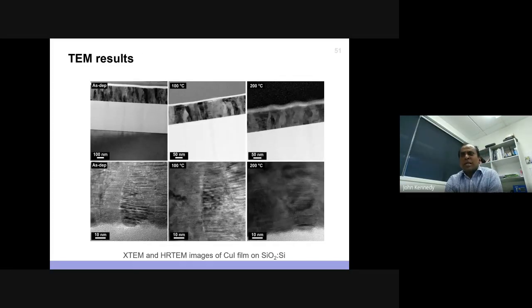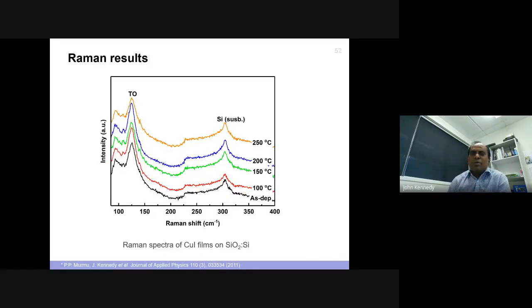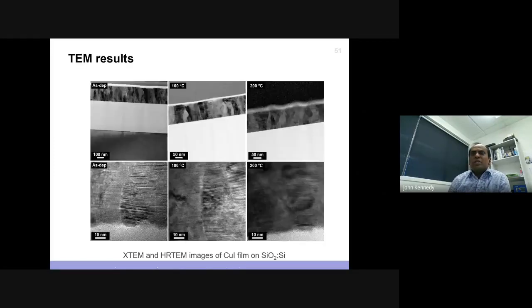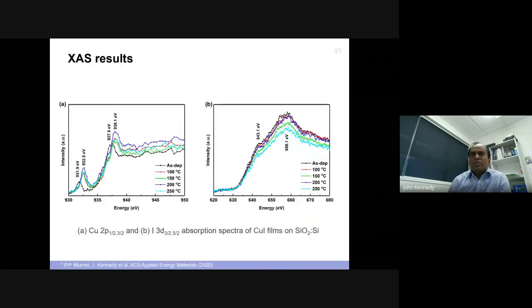Then we look closely at how the microstructure looks in the TEM. We found that some copper metal precipitates form after annealing, which are very tiny nanoparticles. As you can see, some of these precipitates are less than 10 nanometers, and in the figure at 200 degrees C they are tiny, like 5 or 2 nanometer precipitates. So that's interesting, that there are kind of metallic precipitates in your system. We looked very closely with Raman to make sure it still maintains the crystal structure. It's beautifully maintained, and we also looked at the XRD, which is still the same structure.